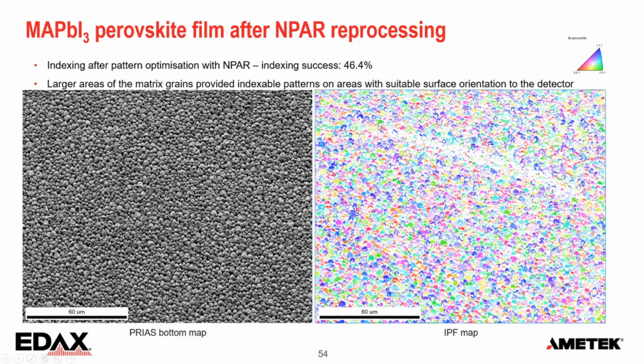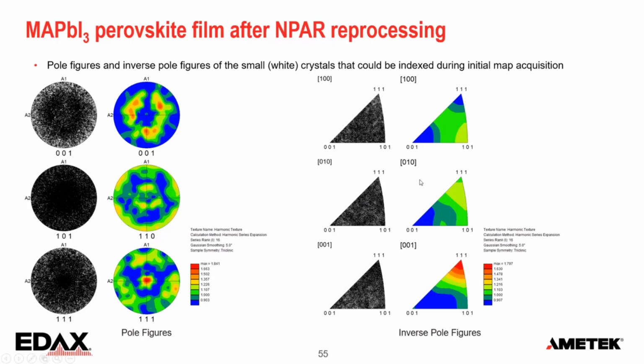And here we have some sort of scratch. Now, if you look at the PRIAS image, it's hard to recognize that scratch. You don't see it. So something has hit it at some point, and it's very sensitive to that. Okay, I'll get to that a little bit more in a moment. Now, this is the larger area. Now I calculated the texture on top of the pole figures. And again, there is a very weak 111 fiber, as you can see here.